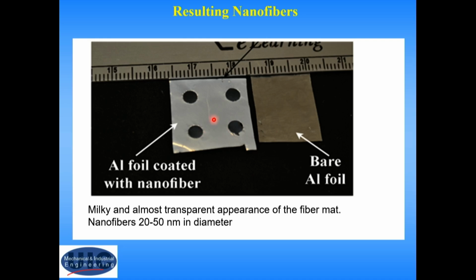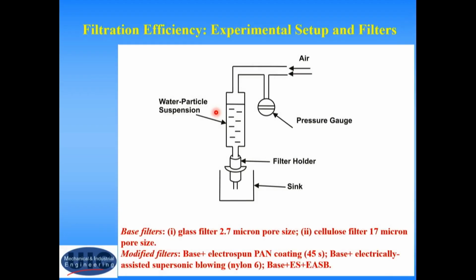So this looks very different from a regular electrospun mat, because it's very transparent, whereas the regular one is very milky. It's very different. So you see the surface through it. And nevertheless, it's fully covered by these fibers. Now, we did some filtration experiments. In this case it was filtration through liquid. I give some references here, so if people are interested, you can see more details.